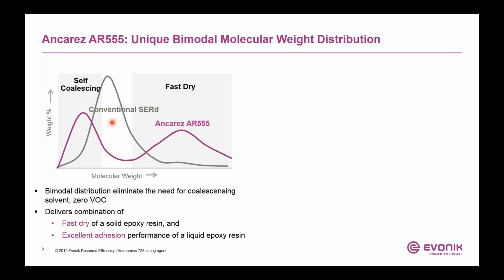Therefore, AR555 does not need a coalescing solvent to form a film. And conventional solid resin dispersion typically contains some type of coalescing solvent. And the higher molecular weight peak of AR555 gives you a fast dry, just like a solid resin dispersion.